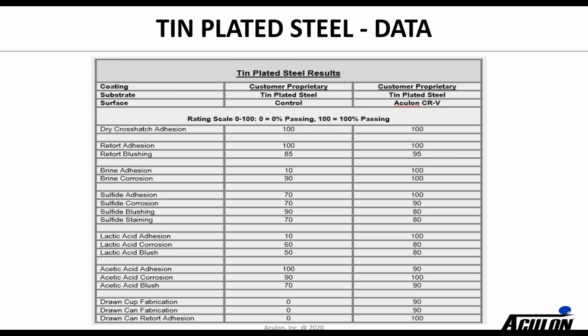So here's some other data that really shows, when you're in a stressful environment with an uncoated substrate, a lot of times you get failures. And so when you look at whether it's drawing the cup, where you actually stress the system in making the can, or whether you're exposing it to lactic or acetic acids or sulfide, you're seeing an improvement of adhesion. So that's both from a chemical resistance as well as mechanical. You can see a pretty drastic improvement if you get the right primer system.